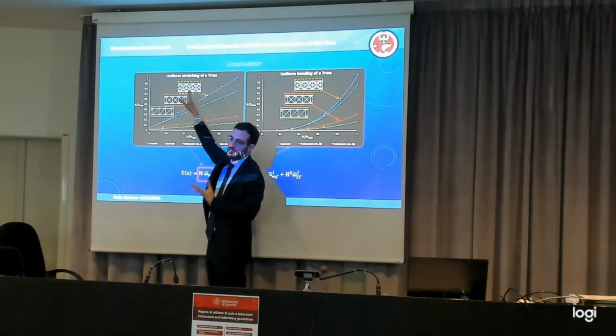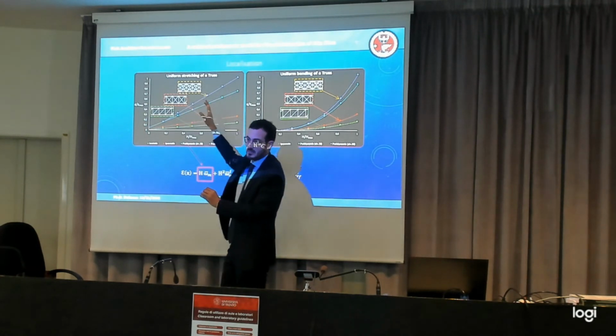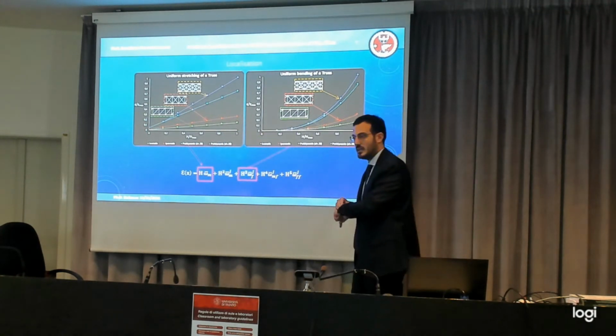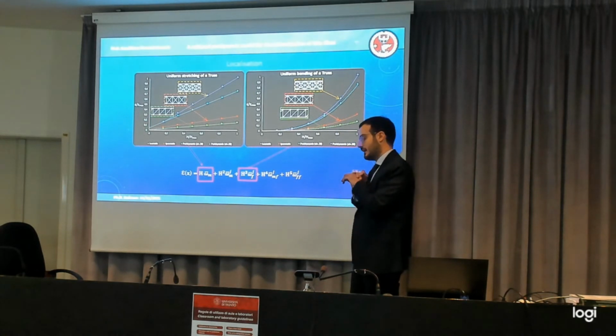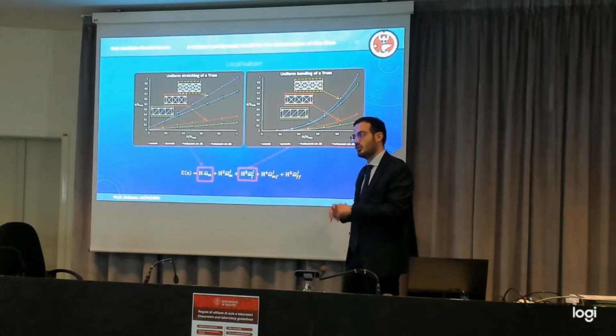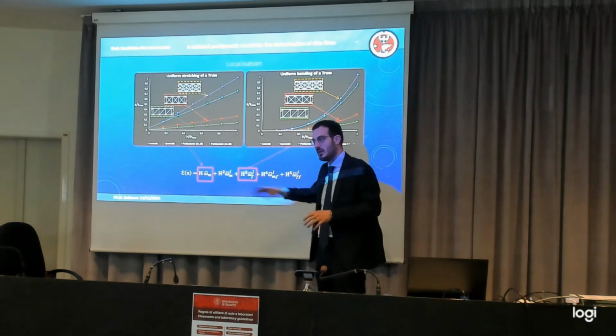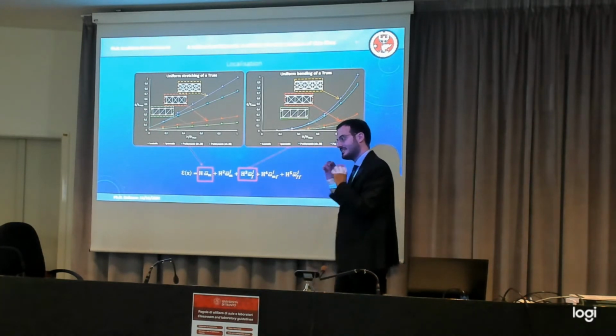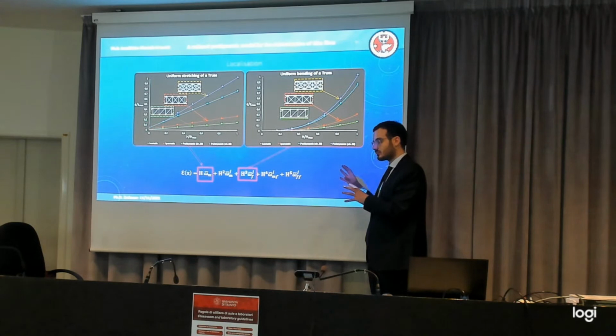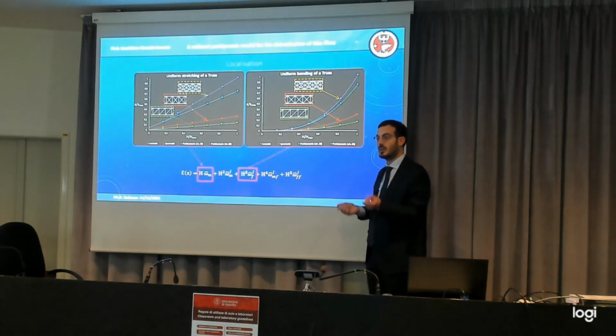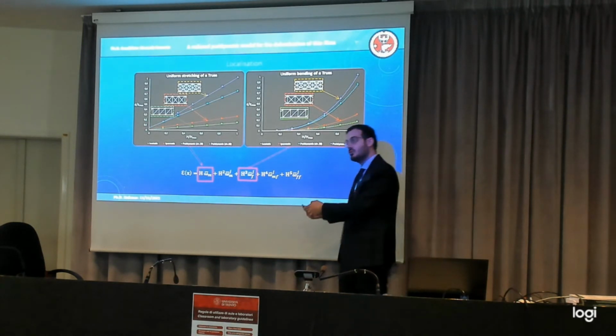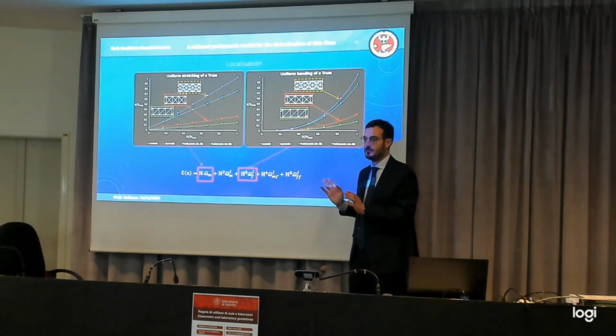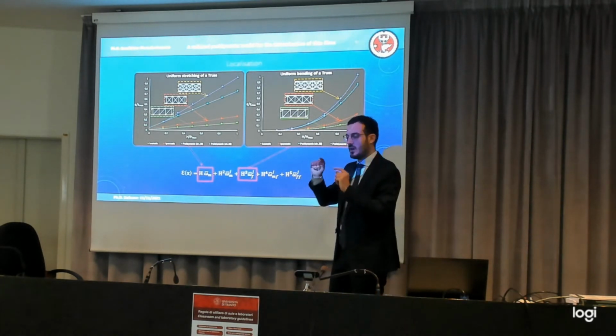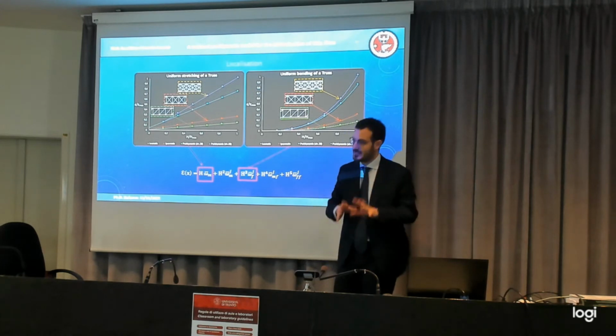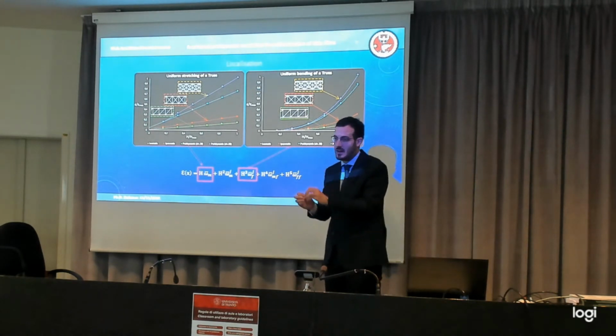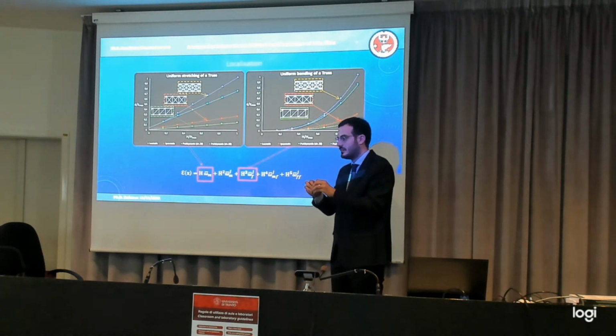and the calibration in that case is specific for that case. Whereas in our model, it is still kept analytical. So you obtain the reduced formulation, and at that level you can still decide how much the critical elongation is in order to reproduce the fracture energy that you want. Once you have the reduced formulation, that is the time that you can act on the parameters to correctly reproduce